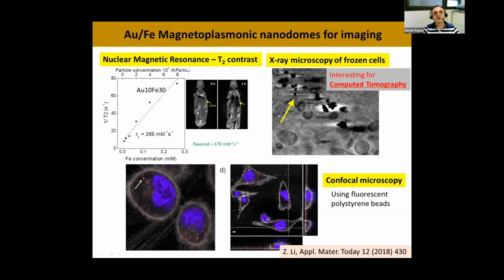Here you see the organelles of the cells, and here in black are the nanodomes, which are highly contrasting black, meaning they absorb a lot of the X-ray energy. And this is interesting for computed tomography, although we have not tried it yet. And another imaging capability is that nowadays you can buy fluorescent polystyrene beads. So now you can image these beads using confocal microscopy.